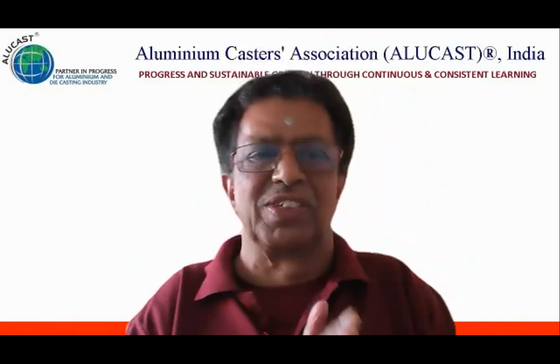There is a question from Mr. Jitendra Parekh: how to achieve elongation of 2% in LM25 alloy? Iron percentage at 0.5, copper 0.2%. Please suggest the T6 cycle temperature range for solution and aging. Okay, beautiful question. Very interesting question. Please maintain the iron not at 0.5. Reduce it. The moment you reduce the iron, elongation will go automatically up.